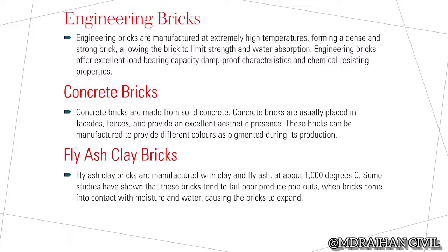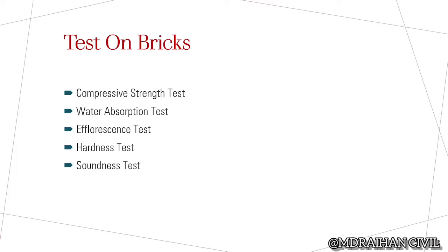Fly ash clay bricks. Fly ash clay bricks are manufactured with clay and fly ash, fired at about 1000 degrees Celsius. Some studies have shown that these bricks tend to fail or produce pop-outs when the bricks come into contact with moisture and water, causing the bricks to expand.